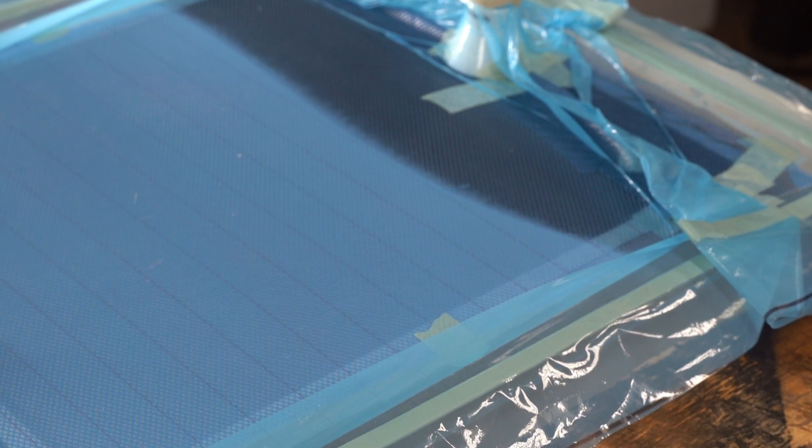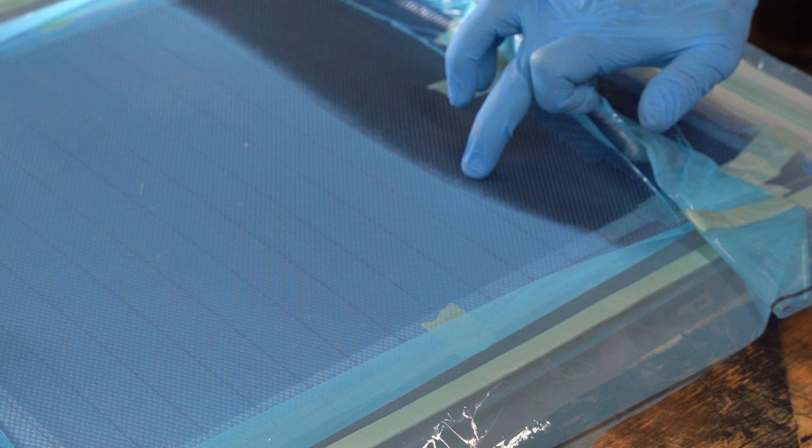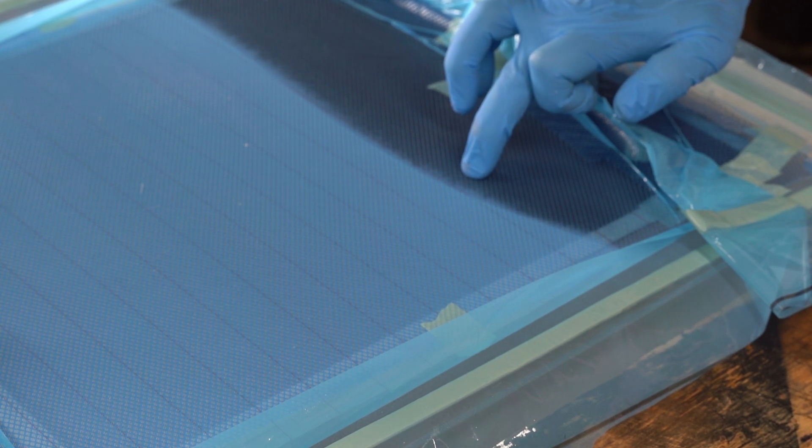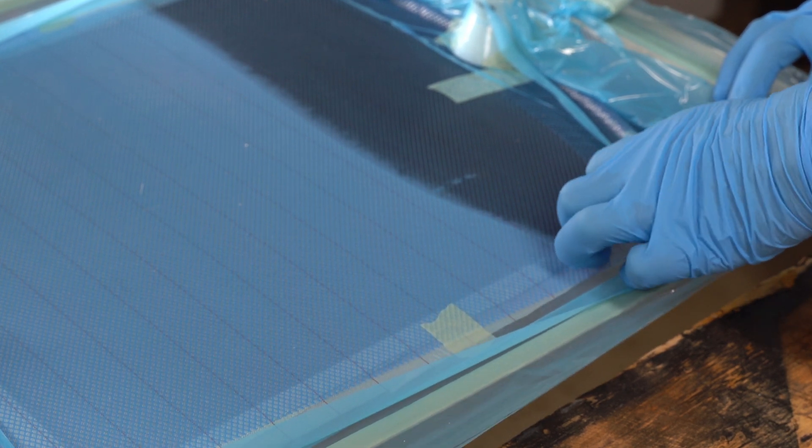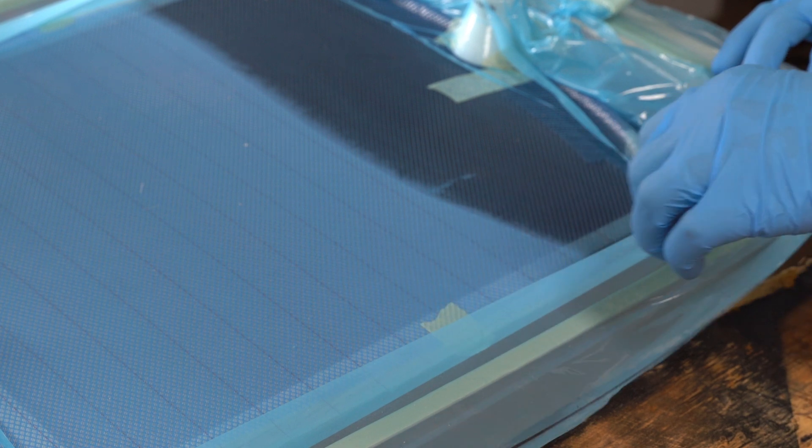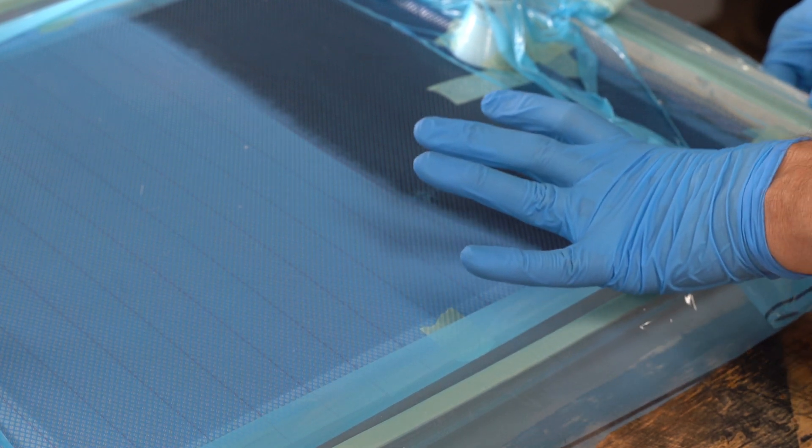Now we get to the interesting part. Right there is a pinhole leak. Although at the moment when I was recording this I didn't realize that was. I'm putting pressure on it trying to figure out where the air is coming from. So I thought well maybe there's a possibility that there's leak here over on the edge and then the air is running underneath the part underneath the carbon fiber and maybe popping up there. So I'm looking for some leaks there along the edge. I'm looking at creases there in the pleat pressing it down trying to make sure there aren't any leaks there.